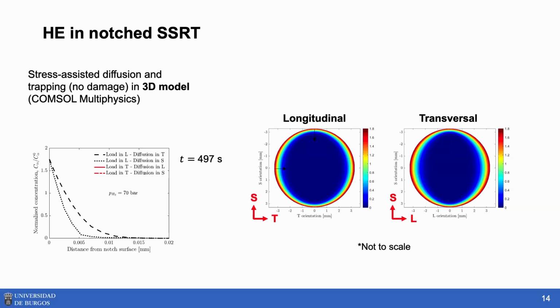But here we are not including phase field, only diffusion and mechanical modeling. And this is not to scale, of course, because as you can see here, the penetration distance is very low, 10 to 15 microns, close to the maximum force. So we have a very small penetration with these trapping and diffusivity parameters.